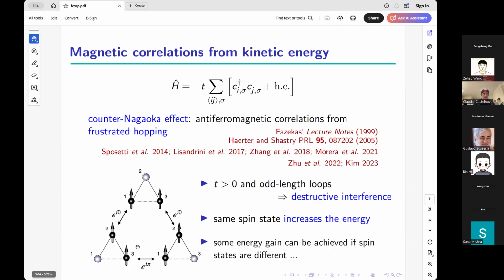Let's see it in the picture shown here. If I assume a ferromagnetic configuration as shown here, I have a single triangle, a hole at site 1, and these 2 electrons, site 2 and 3. Let's imagine we hop the hole around the triangle. So we exchange it. Let's go up first from bottom left to top. We exchange 1 and 2, and then we exchange 2 and 3 going down to right, and then 3 and 1 going back to left. We have hopped around. We have come back to the same configuration.